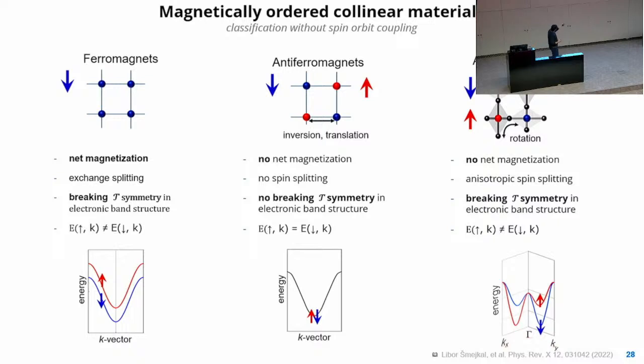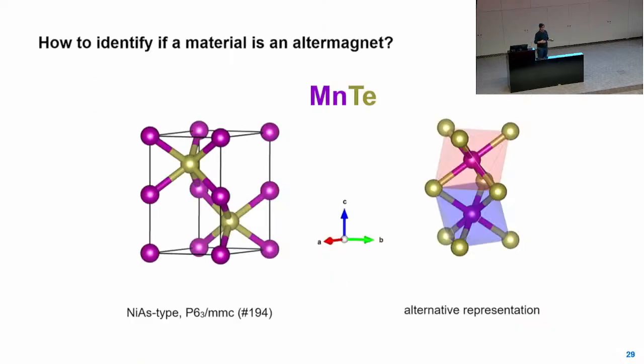And that means, in general, again, the energy of the spin-up electron is different from the spin-down one. And that means we can again have these blue and red bands. And in fact, the splitting in these systems can be equally strong as it is for the ferromagnets, which means now we can have these spin polarized currents in a system which otherwise has magnetic compensation. This means that the hope is that we can have the terahertz speed together with the favorable properties of the ferromagnets in these materials. And just recently we figured out some sort of experimental confirmation for that. And it was done in this kind of material, which is manganese telluride. And I want to show you how we, at least from a symmetry point of view, can understand that this is an altermagnet.